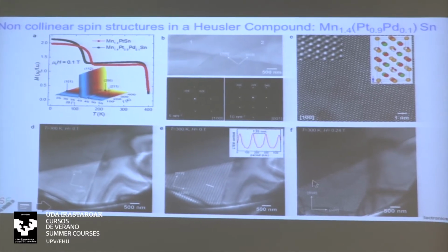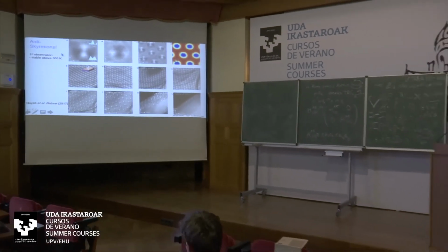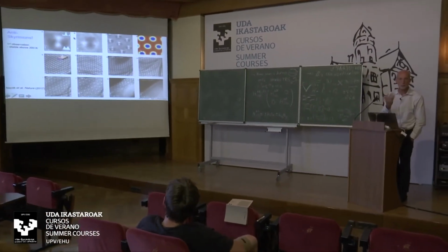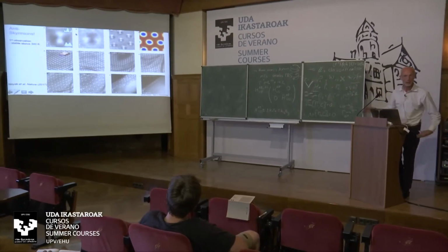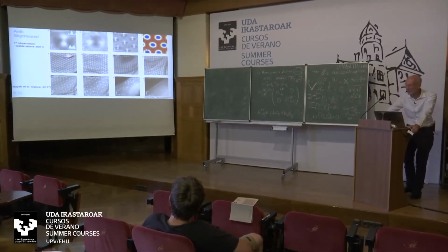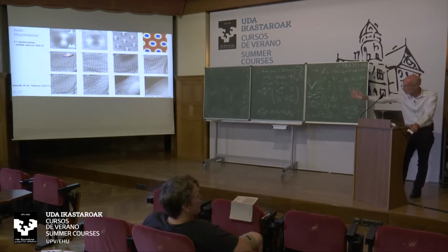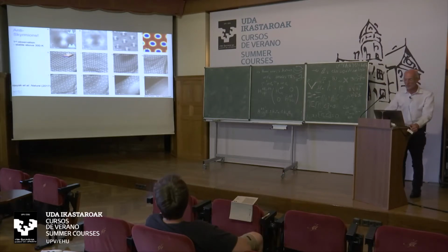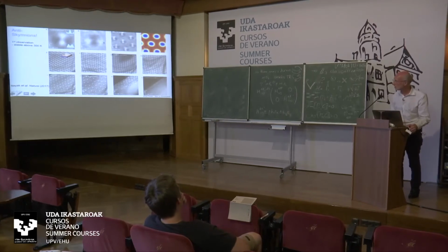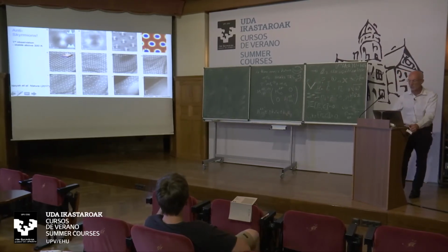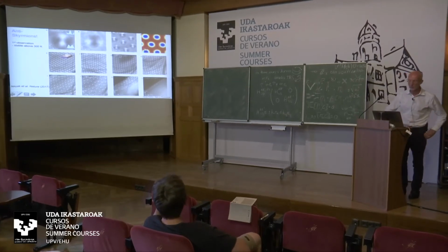And then over here, you may be able to see an arrangement of antiskyrmions. So let me show you in more detail. This is one of these objects, and can you see it looks pretty much like our simulation? Would you not agree? This is the first ever observed antiskyrmion. We published this last year in Nature. And these antiskyrmions, just like skyrmions, form an array, a hexagonal array. They have a certain size and a certain separation. We can mimic all that in our micromagnetic simulations.